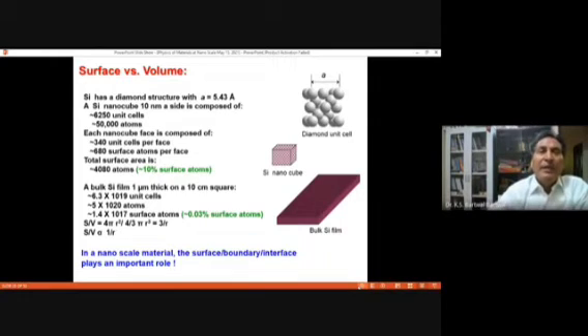For example, I will take the surface to volume ratio. This is one of the important things. At the nanoscale, 10% of atoms are surface atoms, but in bulk, it has only 0.03% surface atoms. What does it mean? In the nano case, 10% of atoms are at the surface. That's why it is a very, very active material. But when the same silicon is in bulk, only 0.03% of atoms are at the surface. So the activity of this material compared to that one is almost 300 times more.